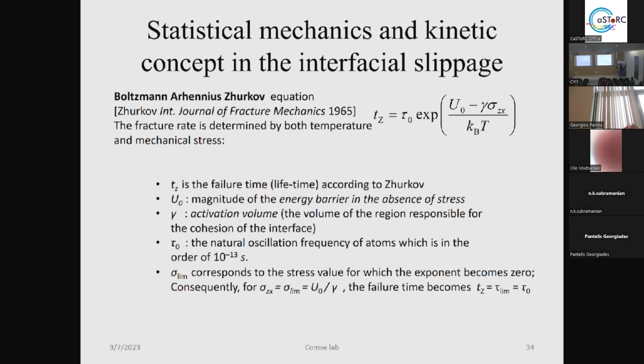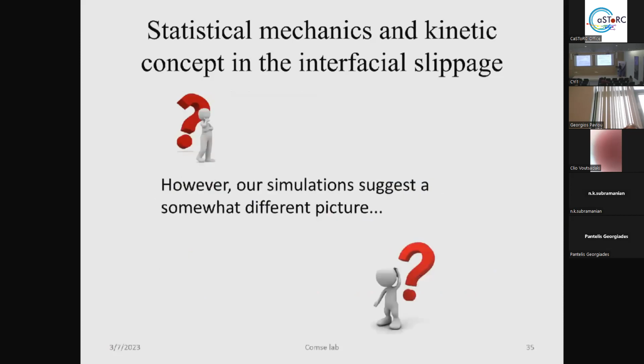The remaining parameters are the oscillation frequency of the atoms, which is in the order of 10^-13 seconds, the tau 0, and of course the energy barrier in the absence of stress, which is the U0, in terms of energy landscapes. How big or small is your energy landscape? Of course, one can easily measure the critical limit of the stresses. If someone takes the exponential to 0, one can see the limit of the stress and the time at which this happened, which in the case of Zhurkov, the limit of time is the oscillation period of atoms. I mention this because we had a somewhat different picture of the system.